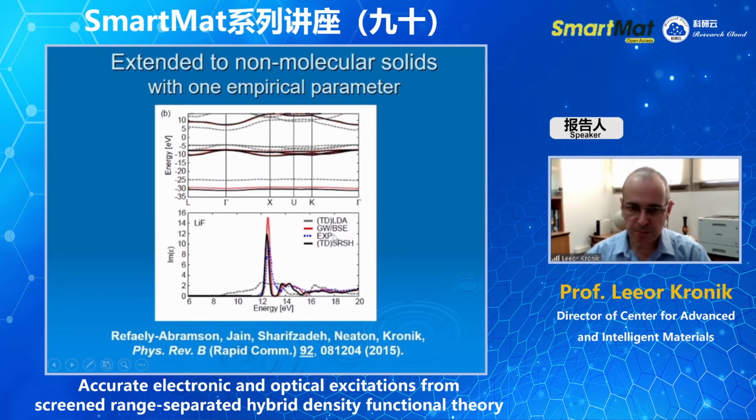But if I do time-dependent LDA or GGA, you see that actually I have this gray line here, which looks nothing like experiment. Agreement with experiment is basically non-existent. The absorption starts way too early and the exciton peak is gone and it's just a mess. So with our time-dependent screened range-separated hybrid approach, which is the black line, you see that full agreement with experiment is restored.